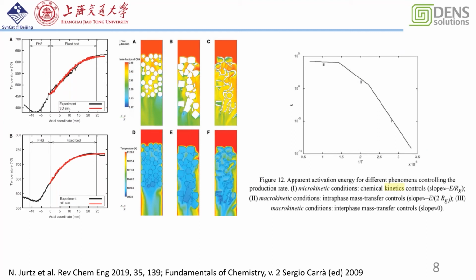We can see that the temperature distribution is very different from the central part to the wall of the reactor, and inside the reactor, when you use a different shape of catalyst, you can see that the mass distribution itself is also very different. That means that for a lot of industrial processes, the mass transferring and the thermal transferring dominate the performance. And here is an apparent activation energy for the catalyst, the same catalyst operated at different conditions. You can see that under the macrokinetic condition, the diffusion dominates everything, and this is very different from the intrinsic kinetic information.